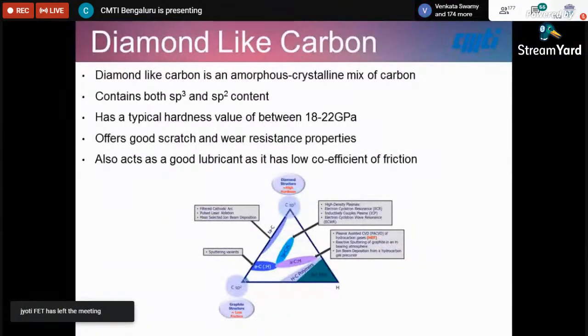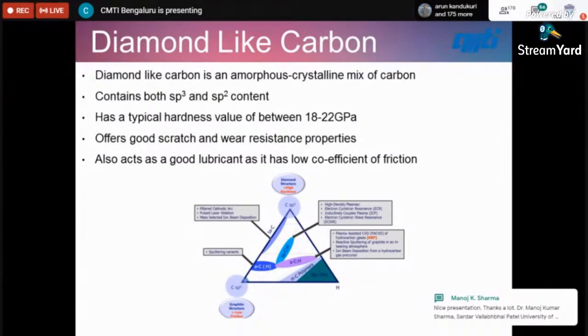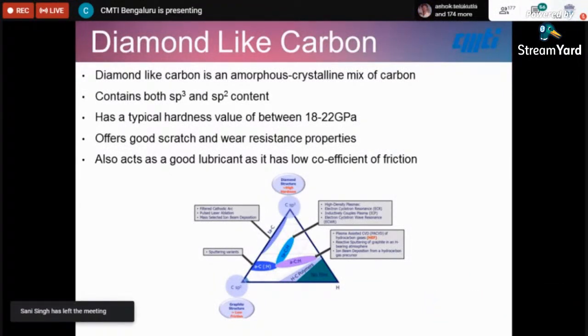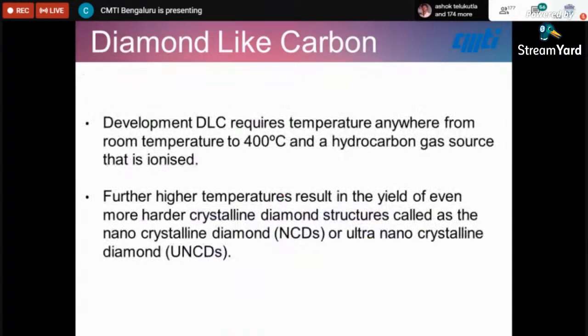These are the two things which we do, diamond like carbon and carbon nanotubes. So what is diamond like carbon? Diamond like carbon is neither diamond nor amorphous carbon, it's something in between, which means it's not going to be as hard as diamond or as soft as carbon. The properties are somewhere in between, and hence it contains both sp3 and sp2 hybridization. Typical hardness is between 18 to 22 GPa. It offers very good scratch, wear, and even IR optical properties, and also is a very good lubricant and has a low coefficient of friction.